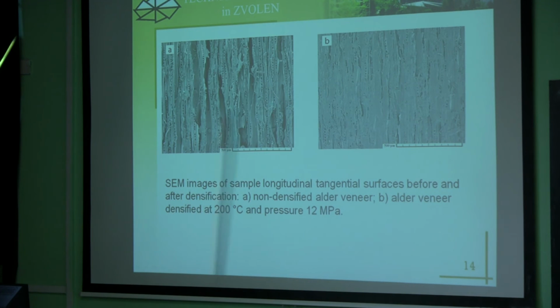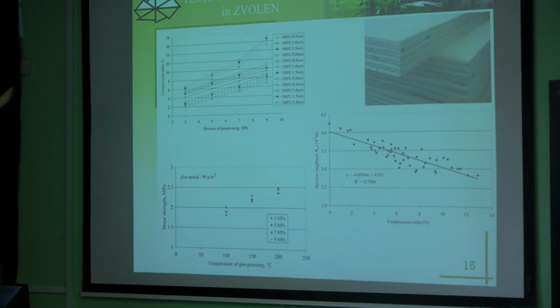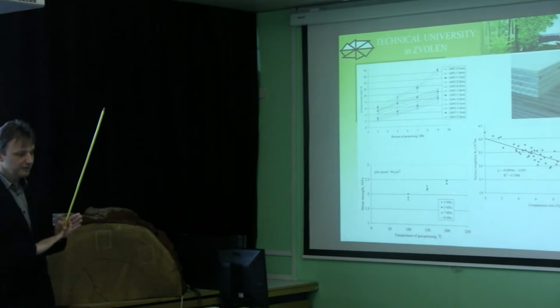From such prepared surfaces of veneer, we prepared plywood, which is also pressed wood, and we can see few relations which I would like to explain to you. Here is the compression ratio in relation with pressure of prepressing of veneer, and we can see if the pressure is low, the compression ratio is low, and if the pressure is very high, the compression is also very high. So the surface of wood is compressed more, and the surface area is very smooth.